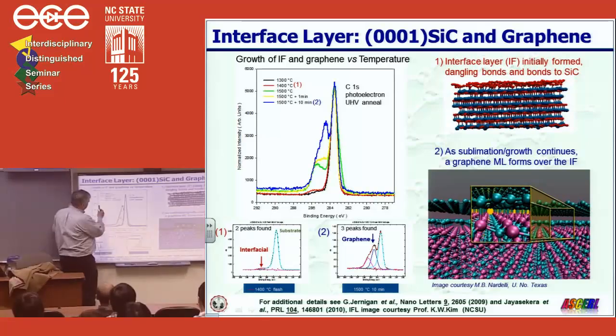When he first started off at low temperatures, so this would be this blackish and reddish curve, you get this little lump in this region here. As he increased the temperature, the lump increased. But as it goes to higher and higher temperatures, then another lump appears, and this thing only shows as a shoulder. So what happens is an interface layer forms first, and then the graphene film grows on top of it.